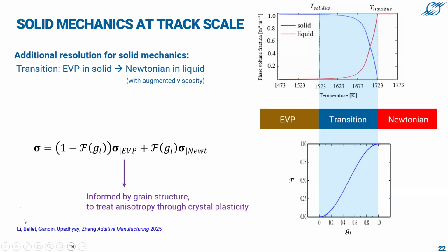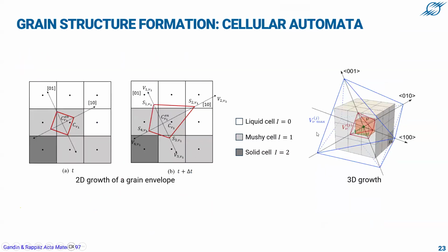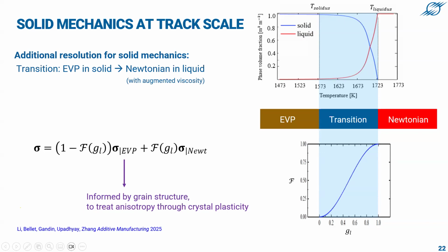In the PhD of Zixuan Li, which has been recently defended, that's what we have done, with a mix between a stress computed by an elastic viscoplastic law and a stress computed by a Newtonian law. Because we are at small scale, we are in the presence of only a few grains, not many grains like in casting of big parts.